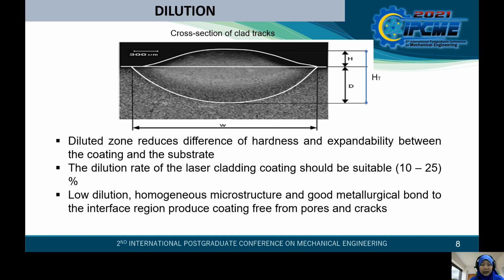Dilution is to determine clad quality. Dilution defined as the ratio of the clad depth in the substrate over the total clad height. The dilution rate should be suitable 10 to 25%. Dilution increase with increase in laser power and decrease with increasing scanning speed. Dilution and molten depth of substrate increase with the rise of laser power. The depth of melt layer must be as small as possible to produce homogeneous microstructure and good metallurgical bonding, and coating free from pores and crack.